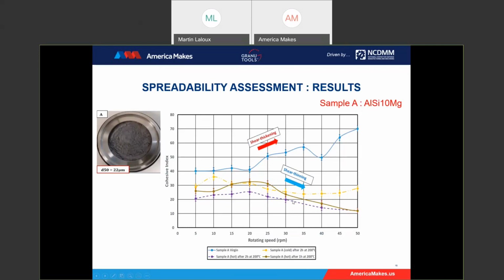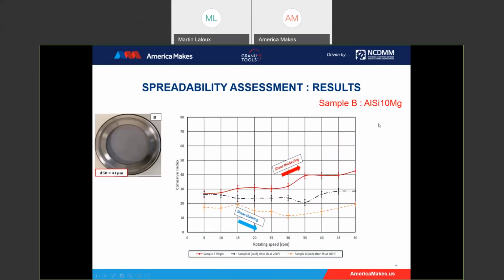So then we observe the same behavior for sample B: the shear thickening behavior for the virgin powder. So the cohesive index is increasing while the rotating speed is increasing. So the spreadability will be difficult at high speed. And we observe here a small shear thinning behavior for the hot powder.